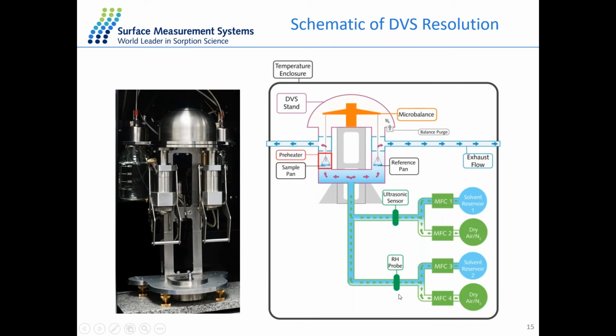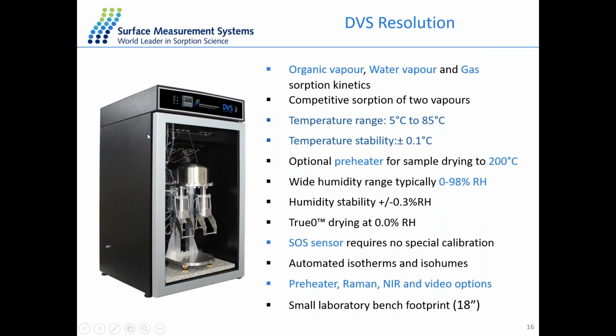And then the sensor will detect this mixture, and the mixture will flow to both the sample chamber and the reference chamber at a constant rate. So the sample inside the chamber here will pick up the moisture, and the mass change will be recorded by the balance. And the whole stand, like this one, will be set in an incubator with a wide temperature range from 5 to 85 degrees, which means you can perform the experiment from 5 to 85 degrees.